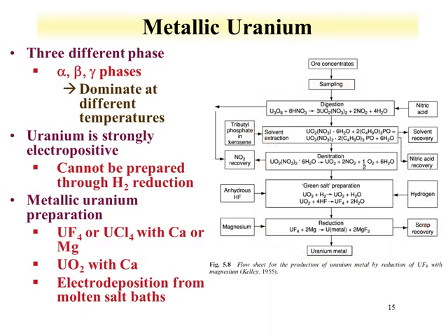And what's done is shown here, where we make fluorides of uranium. We take those fluorides, treat them with magnesium metal, so a divalent metal or even a monovalent metal would be sufficient to reduce uranium from the +4 to the metal state.